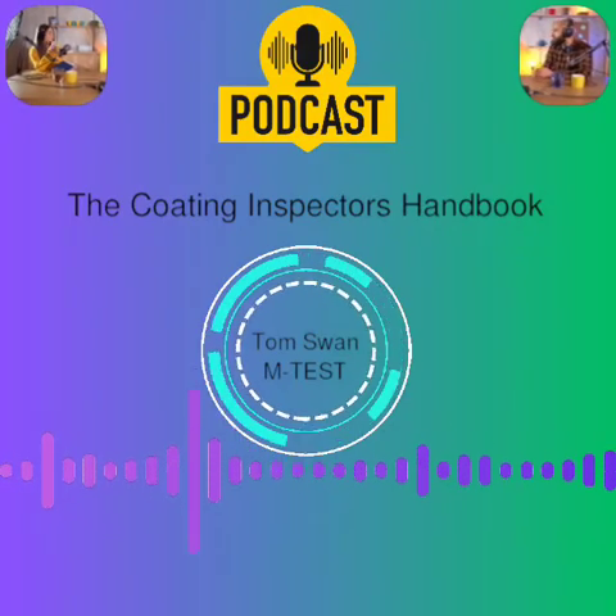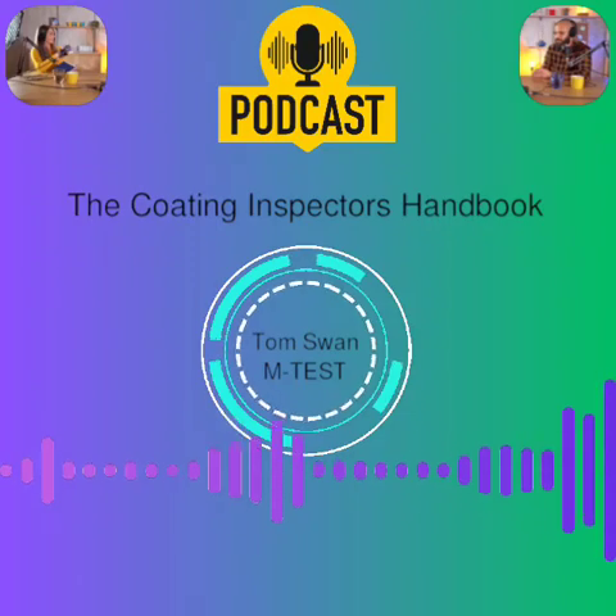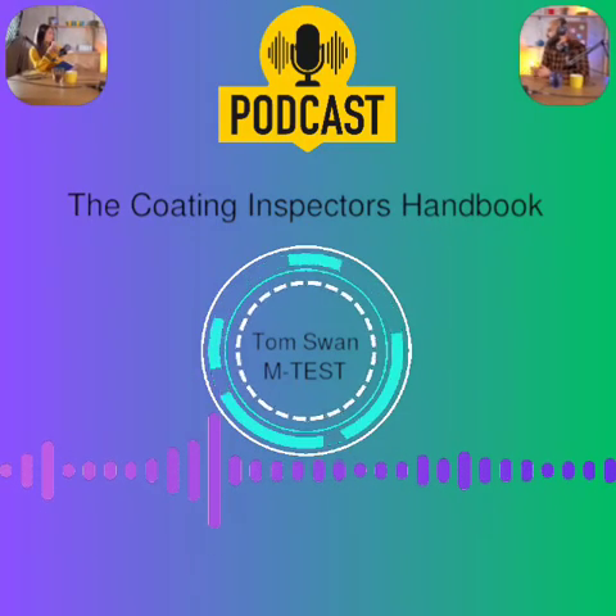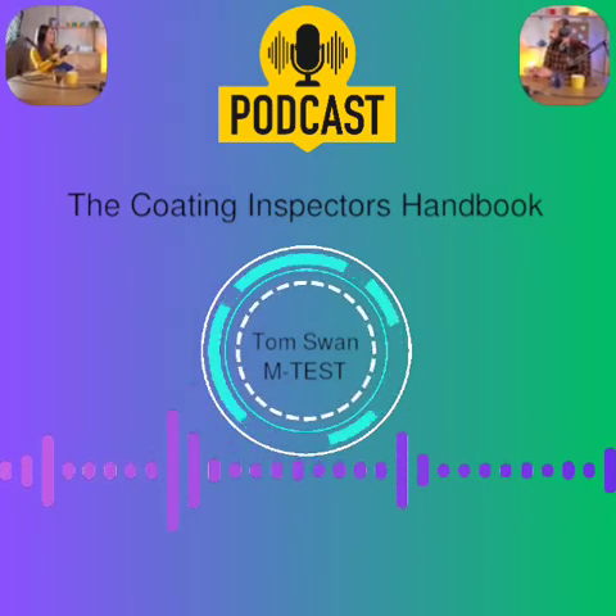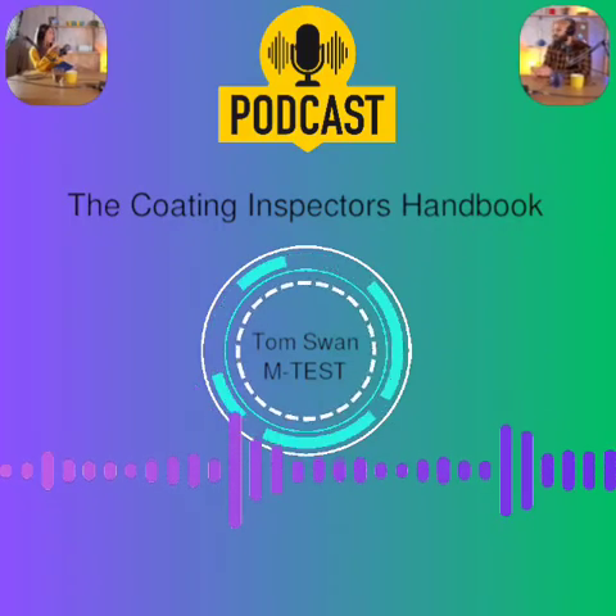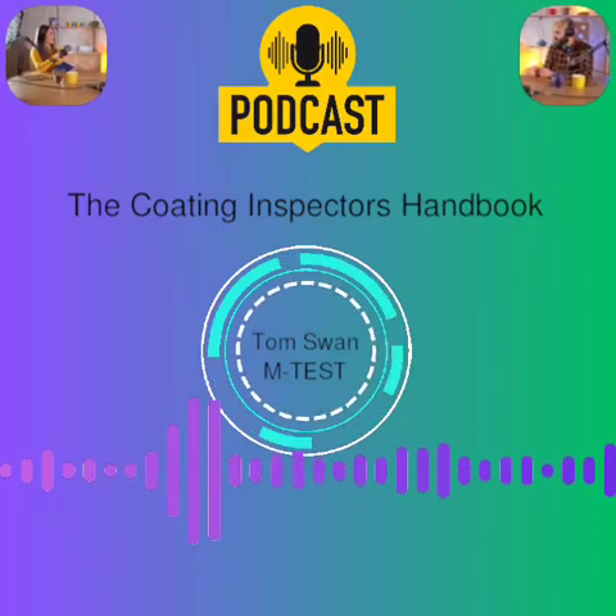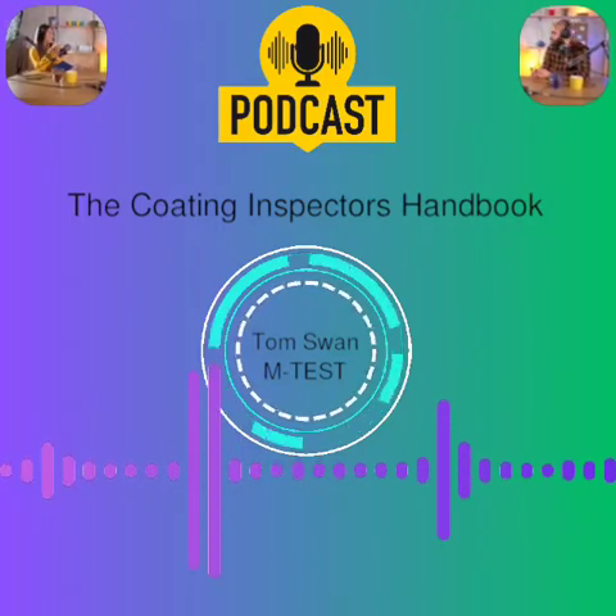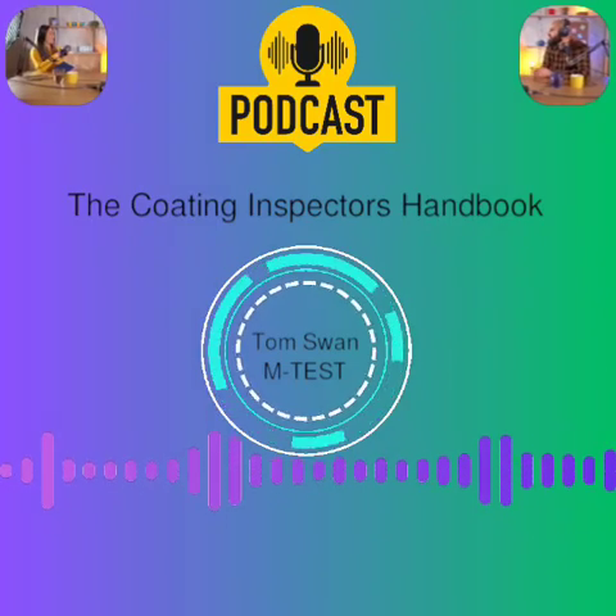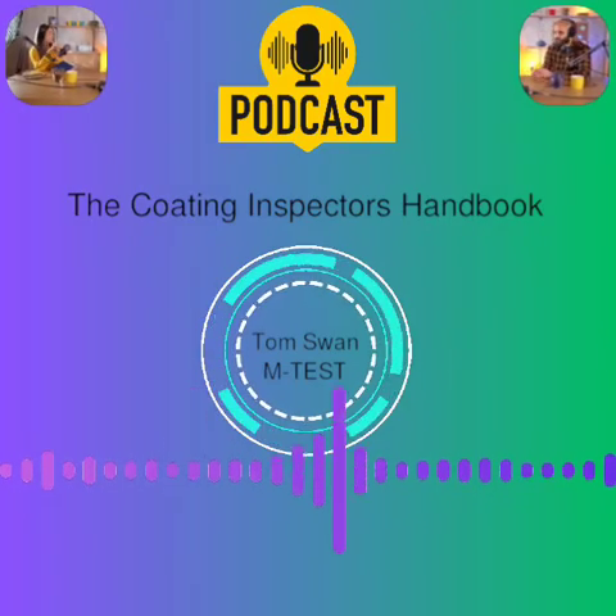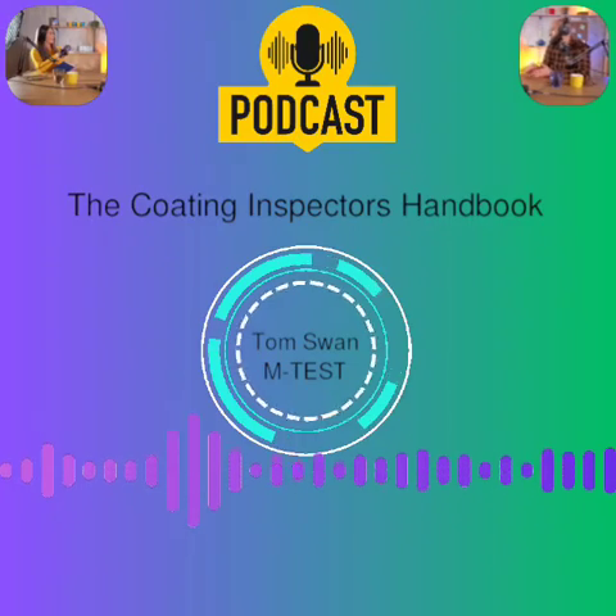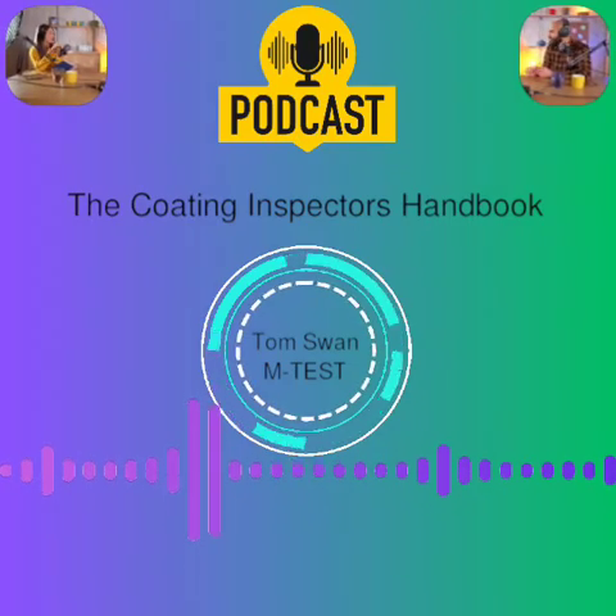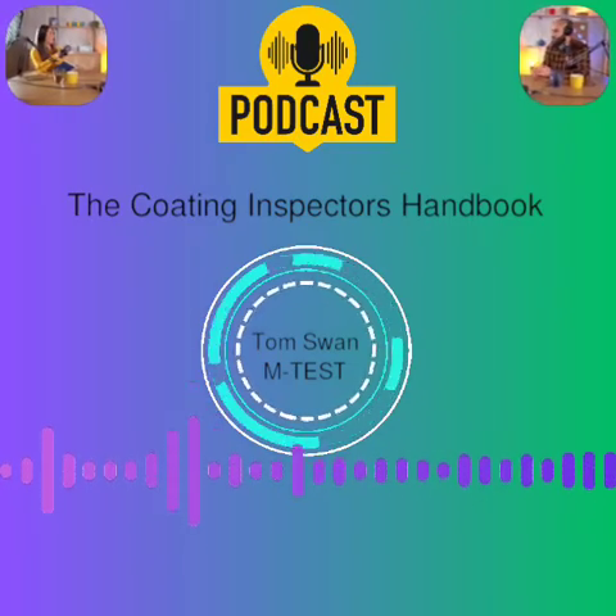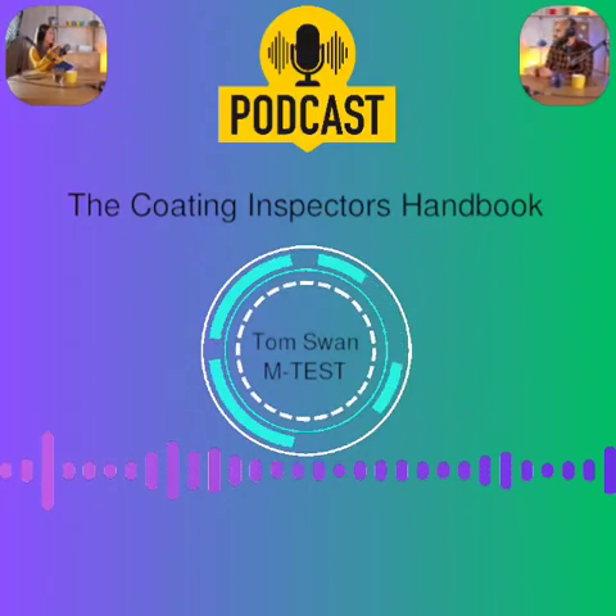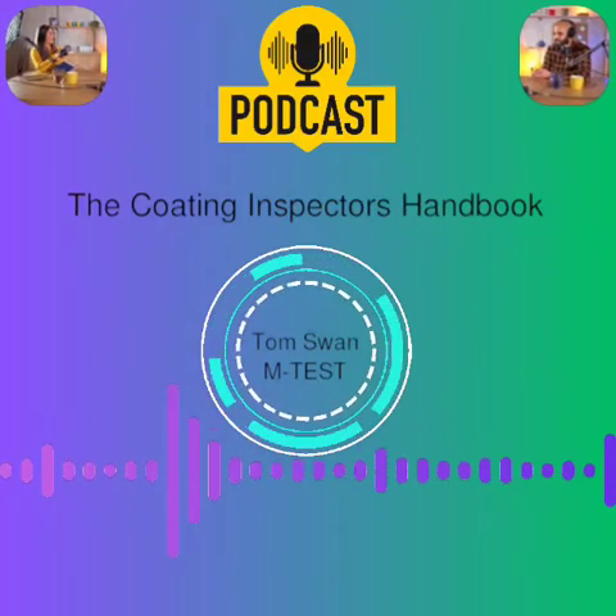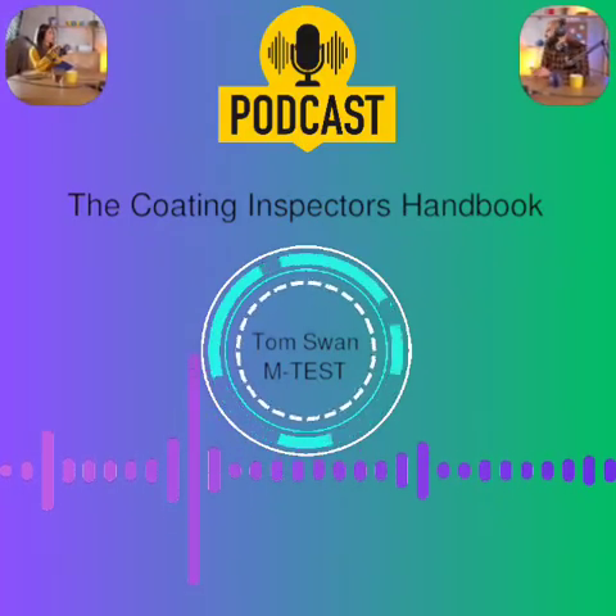So which is more critical to test for, total salts or just chlorides? Depends on the spec and the risk. Chlorides are bad actors for corrosion and blistering, but total salts drive osmotic blistering because it's about the total ion concentration difference. So for immersion, total salts might be more relevant. Often, yes, because blistering depends on that total concentration gradient across the film. For atmospheric exposure to rain, which is pure water, any significant trapped salt, chloride or otherwise, can potentially cause blistering. Specs with really low limits, like 3 micrograms per square centimeter, are being super cautious.